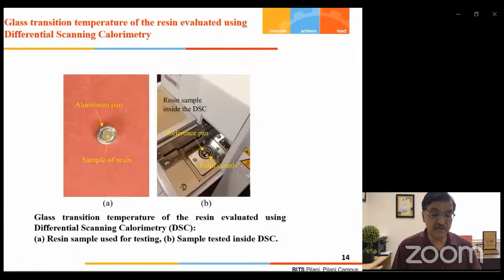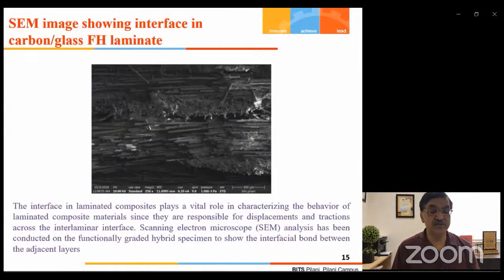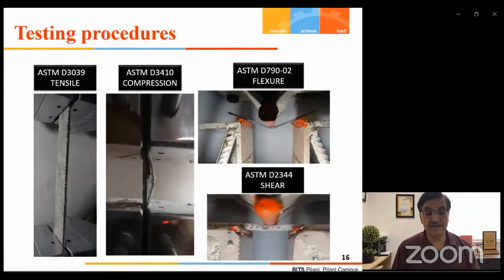A differential scanning calorimeter was used for finding the glass transition temperature of the epoxy resin. The SEM image shown here is from a scanning electron microscope, used to find the interface characteristics of these hybrid and functionally graded composite materials. There are test setups for finding tensile, compression, flexural, and interlaminar shear strength, all done as per ASTM standards.